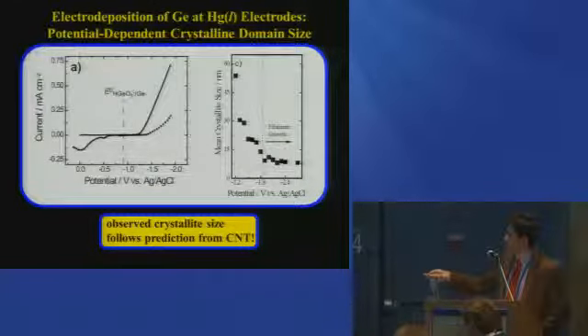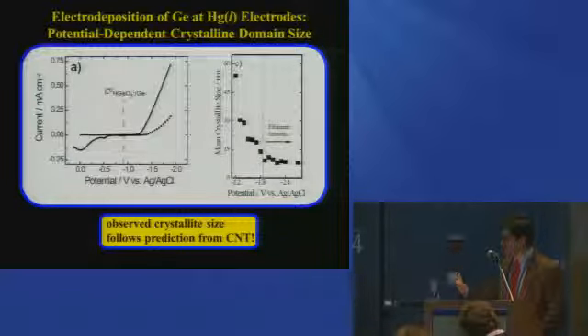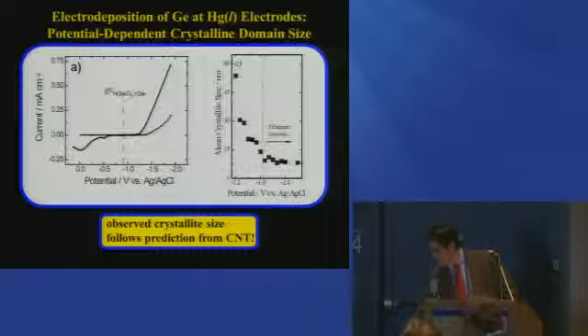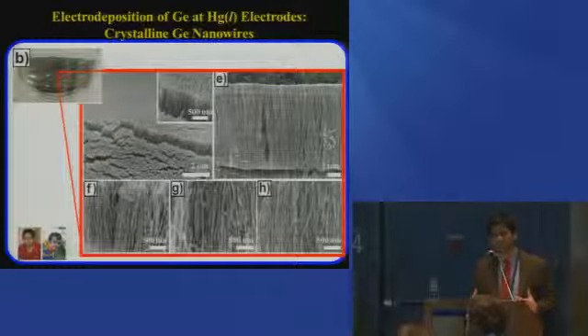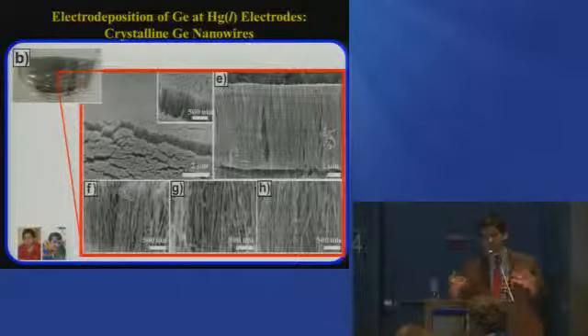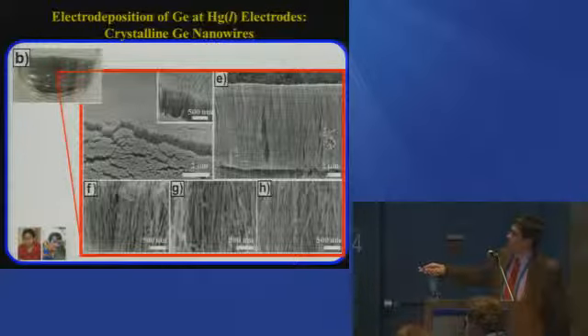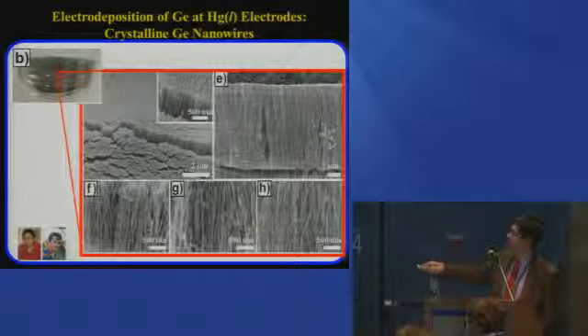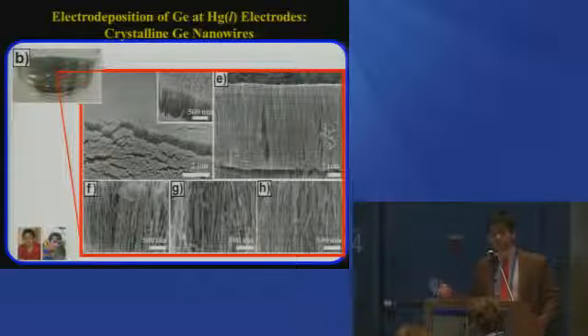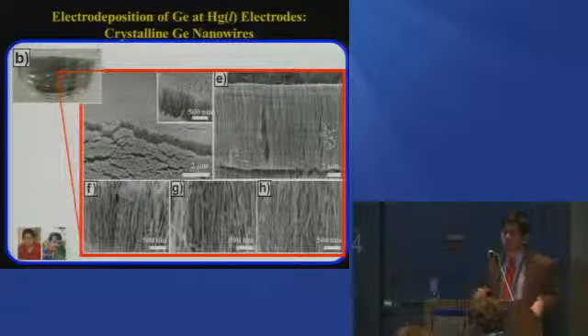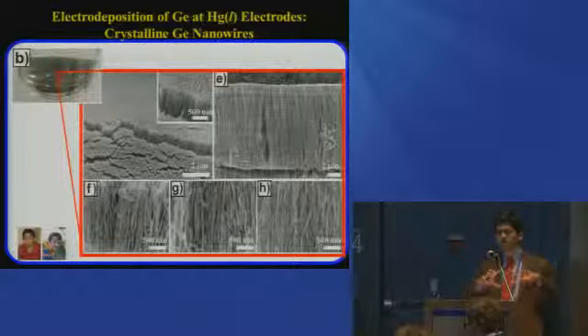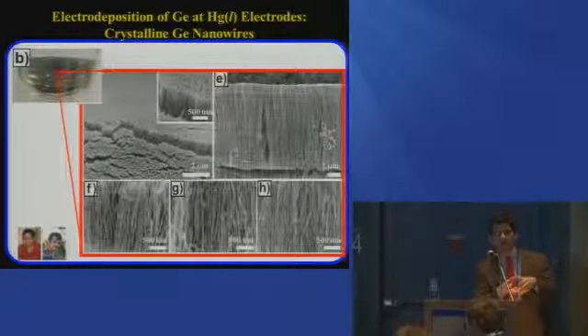What we found is that when we entered this regime out here, when we were really pushing our system, shocking it basically, that dark brown soot wasn't just dark brown random crystallites. What we were getting was these highly ordered, very dense, monodisperse films of germanium nanowires, crystalline germanium nanowires, that were literally being, if you want to think about it, electrochemically extruded from this mercury blob.